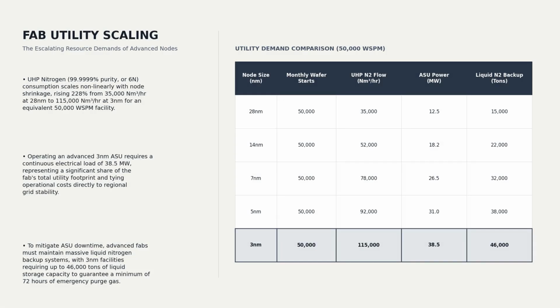Ultra-high purity nitrogen consumption scales nonlinearly as transistors shrink. For a standard facility processing 50,000 wafers per month, demand rises from 35,000 cubic meters per hour at 28 nanometers to 115,000 cubic meters per hour at 3 nanometers. This gas must achieve 99.9999% purity to prevent wafer oxidation in process chambers. Even part per billion levels of moisture contamination will ruin entire production runs.